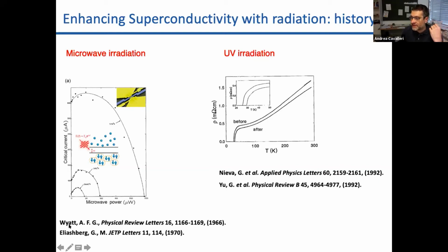This is described very nicely in the Eliashberg theory that came after a few years and gave a very nice explanation of these effects. Here I'm showing critical current enhancement as a function of microwave power. And in these cases, what people have shown, and this is reasonably well understood, is that one can enhance Tc in this driven state by something of order, let's say, tens or hundreds of millikelvin.